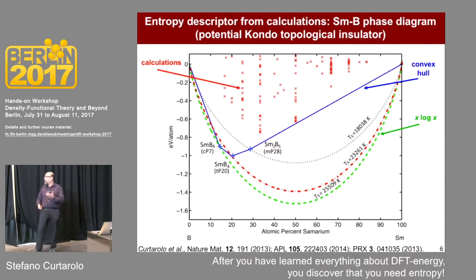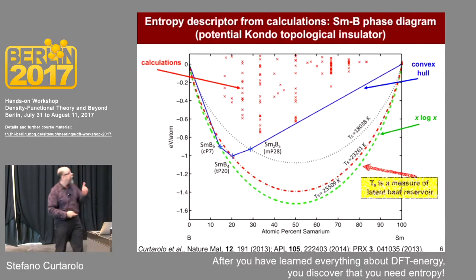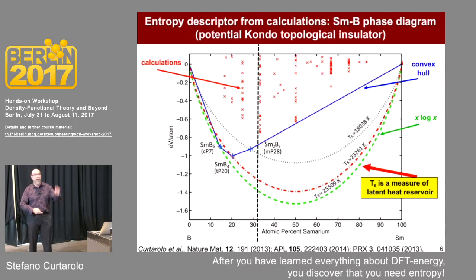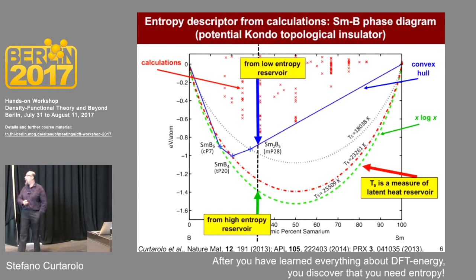Okay, what these points represent then, these arrows would represent your equi-heat exchange between the reservoir and the system. Let's see what happens when you make these things. If you come from an environment of low heat reservoir, then you will follow the recipe and you will hit this blue tie line and go to samarium boron 4. But if you come from a reservoir of high heat, because the temperature is high, or because the entropy is high, or because both are high, then you will reach these lines.